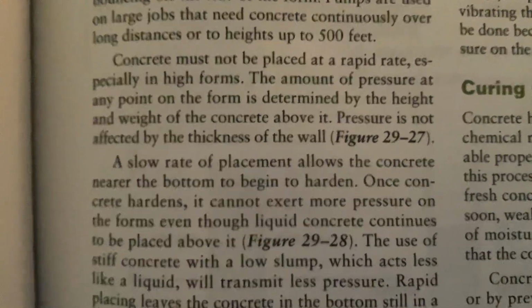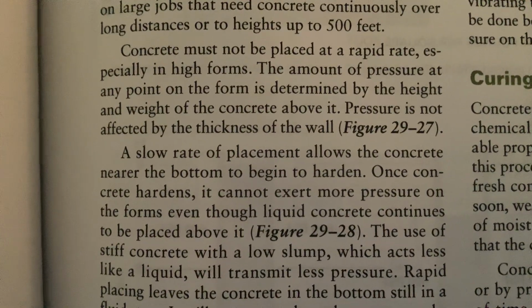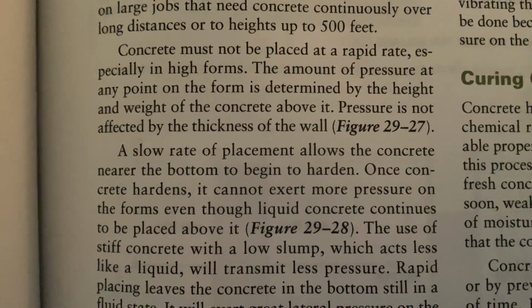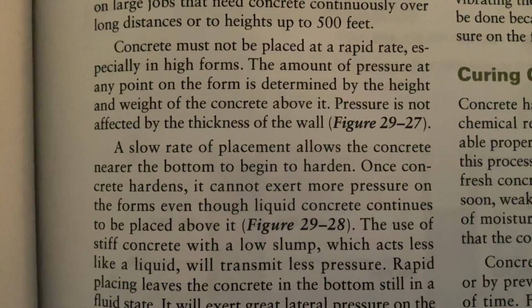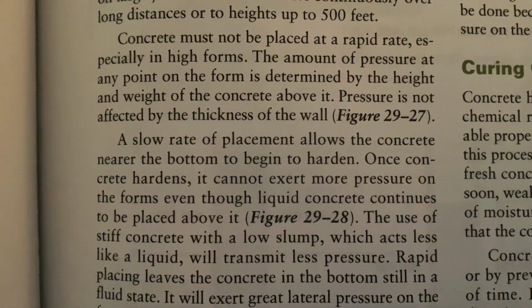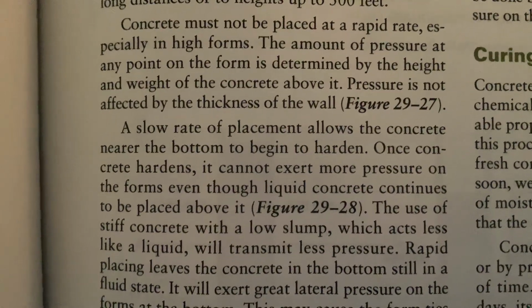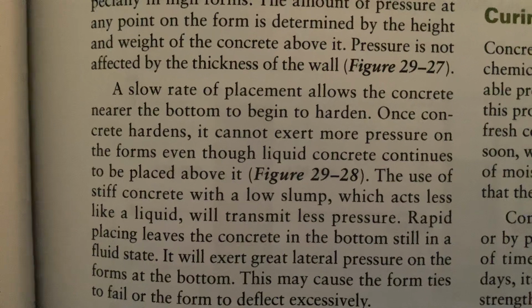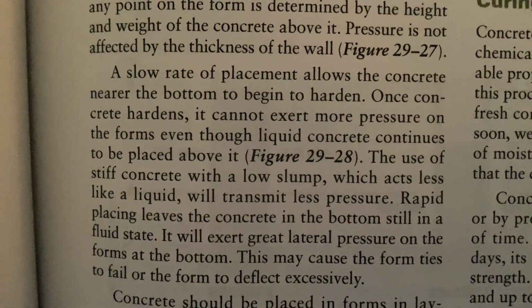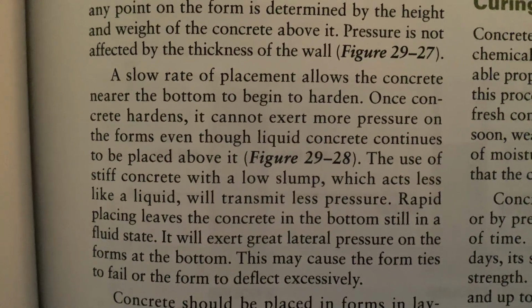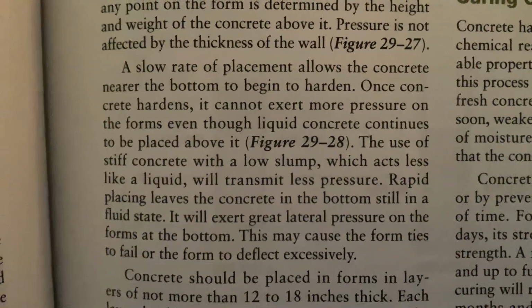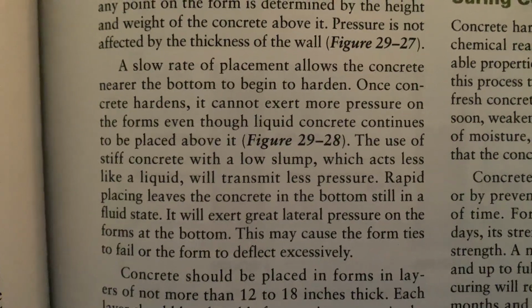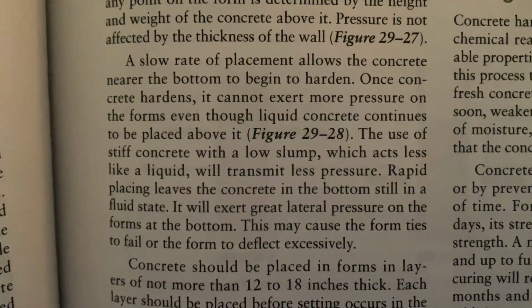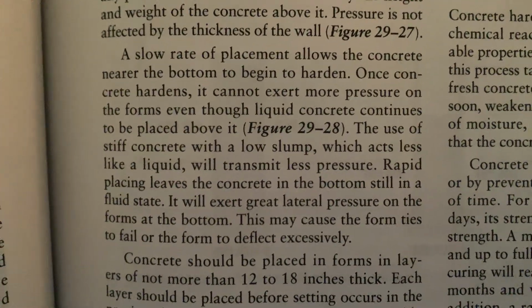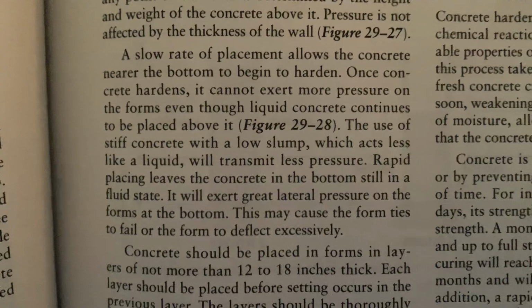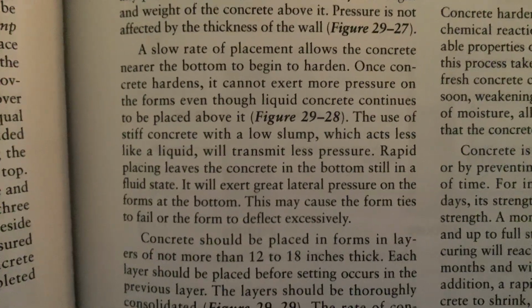Concrete must not be placed at a rapid rate, especially in high forms. The amount of pressure at any point on the form is determined by the height and weight of concrete above it. Pressure is not affected by the thickness of the wall. A slow rate of placement allows the concrete near the bottom to begin to harden. Once concrete hardens, it cannot exert more pressure on the forms even though liquid concrete continues to be placed above it. The use of stiff concrete with a low slump, which acts less like a liquid, will transmit less pressure.